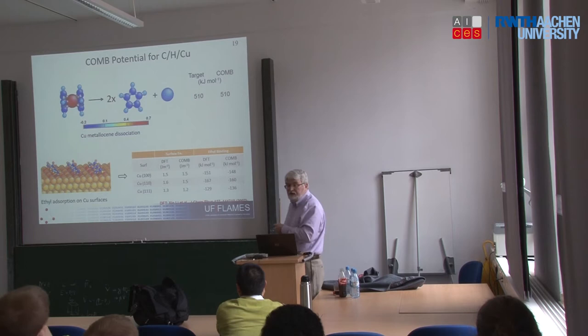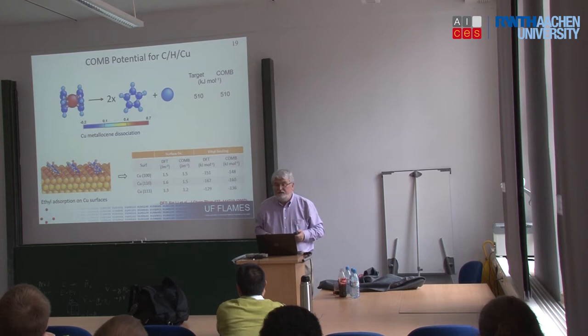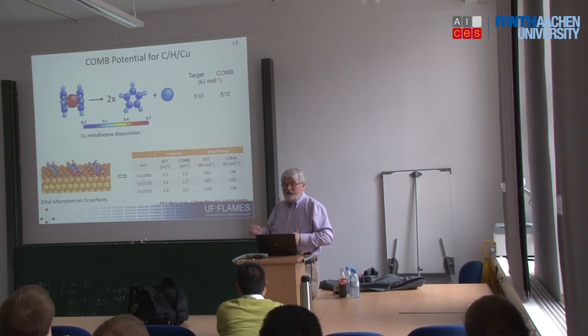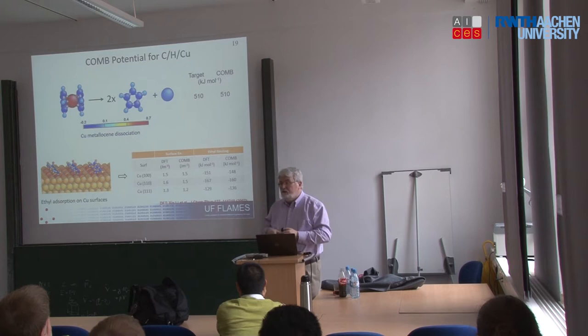And again, now we have this potential. These kinds of calculations are going to be 100,000 times cheaper, or 10,000 times cheaper, than the DFT calculations. We're essentially capturing the right physics of this. So we can look at these things. Now, dynamically, we don't have to just do static calculations. We can actually deposit these things, and we've done that. Let them rain down slowly on the surface. Let them move around and find optimum positions. Maybe they break up. Maybe they move off. We can do all those things dynamically, which is very, very hard to do with ab initio and would be very, very expensive.